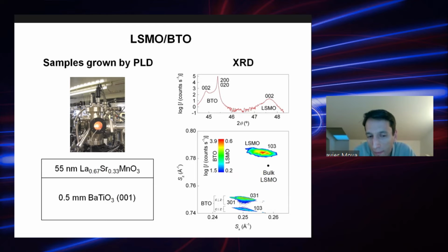When you look at this sample at room temperature, as I said, barium titanate is in a tetragonal phase. So if you perform X-rays, what you see is that BTO is effectively tetragonal, so you have these two peaks corresponding to the direction of the z-axis, whether it's in plane or out of plane. And then you also see the peak of the film, of LSMO, which is pretty broad, because the strain mismatch between the substrate and the film is quite large, so you have relaxation.